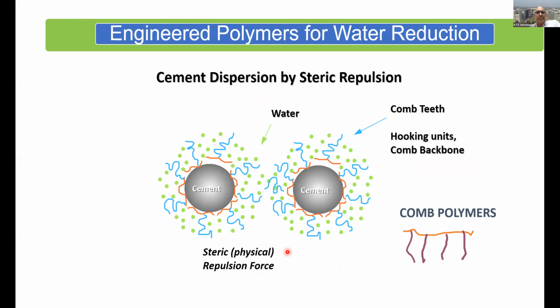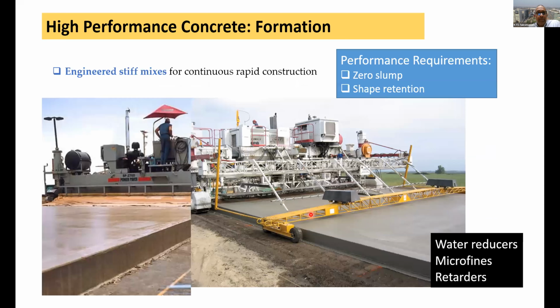These are engineered polymers that are specifically engineered so that they have this comb-like structure with these teeth sticking out. Each of these polymers sticks to the cement grain. It produces steric hindrances between cement grain particles and basically deflocculates the structure of the cement grain suspension. It starts flowing very easily. So this is now a field in itself of how to control the flow behavior of cement paste and concrete. And we are basically bringing in material processing of other domains to help us in this job.